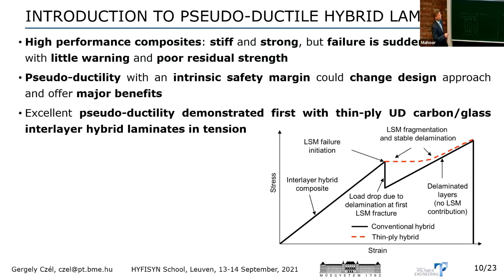Then we have a major load drop when the low elongation component, let's say the carbon epoxy in a glass carbon hybrid composite, breaks. So we have a load drop, and then the high elongation layers, namely the glass epoxy layers, can take the load and give a further rise to the stress strain graph.